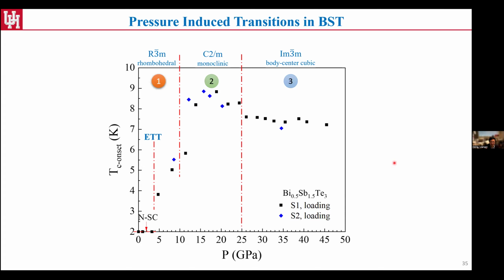So honestly, we're betting more on phases 2 and 3, right? Because for phases 2 and 3, we do have these very clear structural transitions. That gives us a higher successful rate experimentally. So to be honest, that's what we did. Once we first did the experiment, we were quenching in this region and then here. But later on, we thought we were already doing so many experiments, so why not give a try on this region, even though there's no structural transition? We're not really expecting we can retain anything, but we still want to see what's happening experimentally.